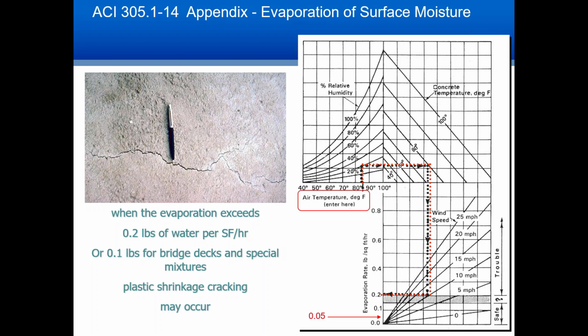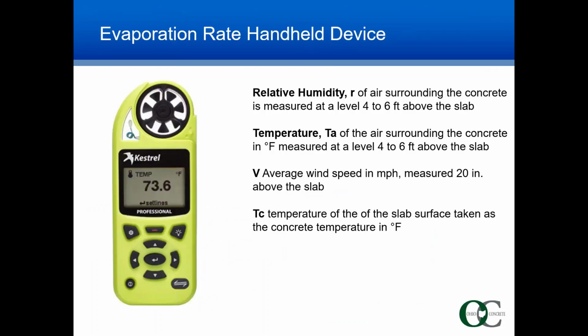With some concrete mixtures, such as those containing certain pozzolans, cracking is possible even if the evaporation rate is below 0.1 pound per square foot per hour. Concrete containing silica fume is particularly prone to plastic shrinkage cracks because of a lack of bleed water. Cracking can develop with evaporation rates as low as 0.05 pounds per square foot per hour.